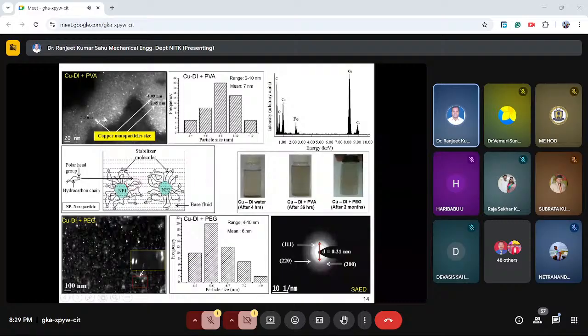were obtained in this sample. However, after 36 hours of the collection of this sample after the experiment, it is found that sedimentation of particles still takes place. It was after 4 hours only in DI water, and after 36 hours by visual inspection here. So what is the problem behind it? Due to the high concentration of hydroxyl groups in PVA molecules, they do not adsorb extensively on the particle surface, and they can detach after some period of time. Then the particles start to settle down.